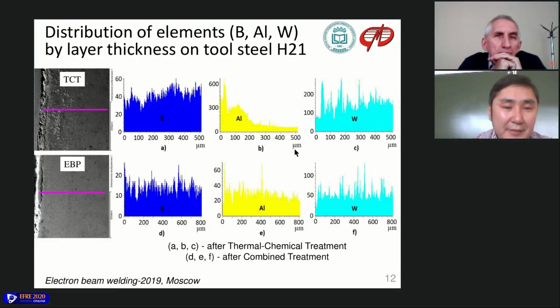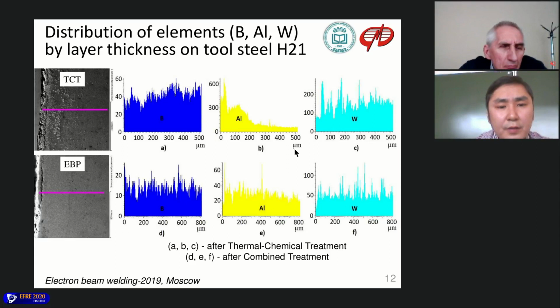So by this time, we haven't finished EDS and XRD analysis for this steel yet, but I can show the results which we obtained on H21, which is an analog. Take a look at the aluminum distribution after TCT, you can see that the maximum concentration is on the top of the layer, then the concentration gradually decreases in the direction to the base metal. And after EBP process, aluminum distribution is more even.